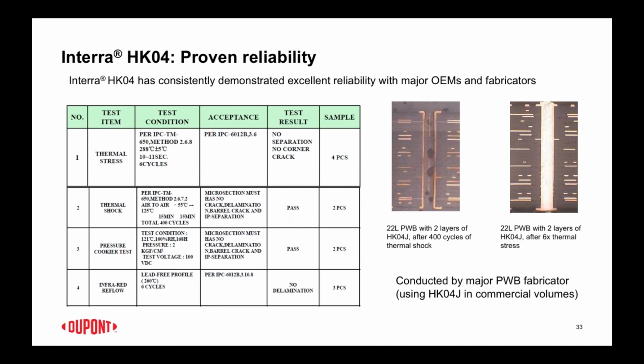And it's proven technology. Like I said, this technology was introduced well over 15 years ago, and we've passed every single IPC test, thermal, mechanical, pressure cooker, any type of reliability test. In fact, when typically a board is going through this reliability testing, it's the other material that fails before our material does, because it is so robust. And this is done by major PWB manufacturers, who have all done this test in multiple sites for multiple customers. So we have a wealth of information on reliability of this technology.